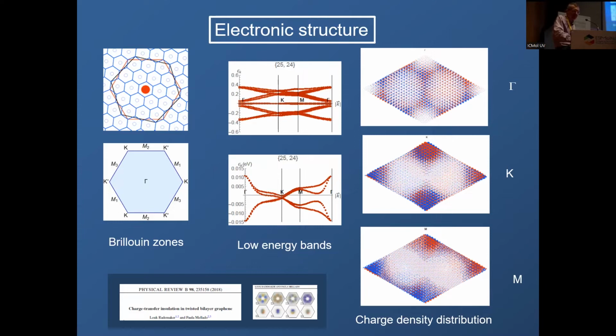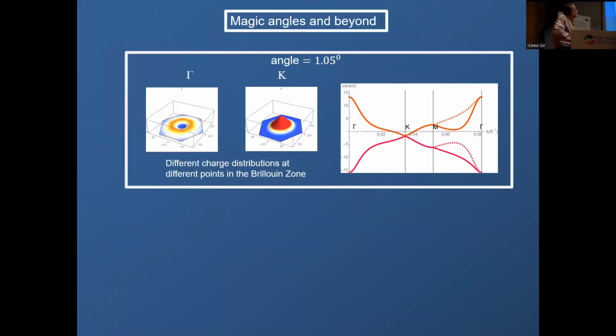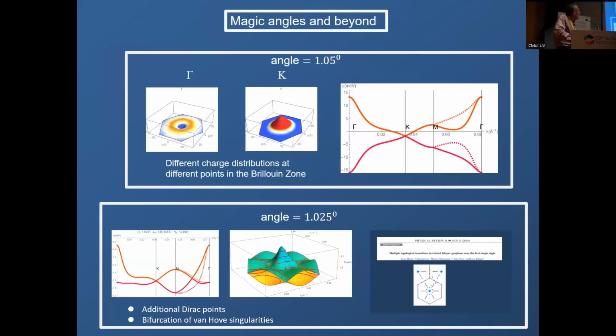The bands are flat, but they are distributed in different ways depending where in the band you are. And this is the same picture again. Two different points in the same band show totally different charge distribution in this large unit cell, which is for this twist angle in the order of 10, 12 nanometers or so. And then for very low angles, the situation becomes very complex, but then you have many Dirac points. The topology of these bands is much more complex, in fact, than the topology you have in topological insulators or systems like that.